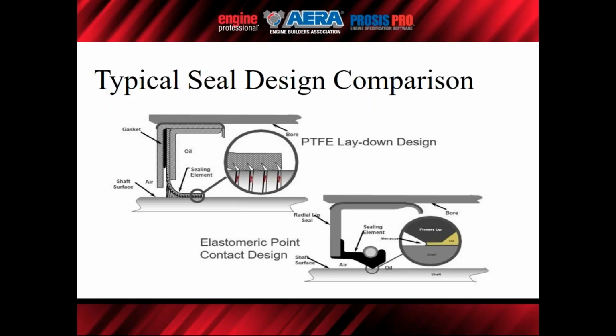Some typical seal design comparisons. Quite honestly, today, the PTFE laydown design is by and large the most popular. The elastomeric seal design is extremely popular too. You can see the garter spring on the back side of that, where it's actually contacting the interface. That's what controls the point load on the seal surface. With the PTFE, you can see where each little channel is cut into that seal surface. There's a cutting action, and it's actually a spiral. So those things, in reality, have a lead that could migrate oil all the way out. But what they do is condition themselves to the shaft, which we'll see in an upcoming slide.